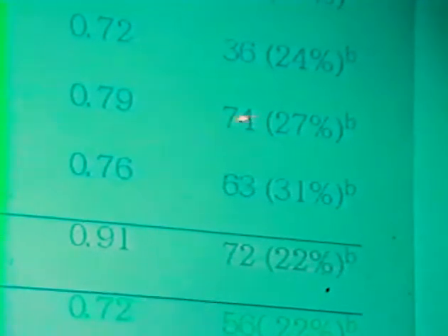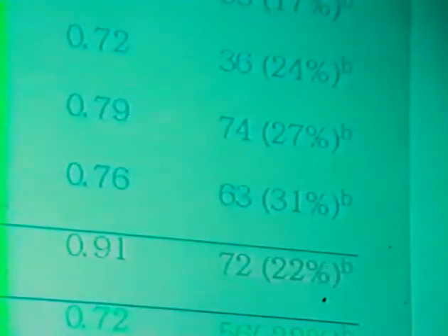And in fact, we get about the same selectivity. But if we look at the relative conversion at 15 minutes and 50 minutes, which is some measure of the self-poisoning by coke, the smaller particles appear to be more stable. They retain about 90% of their activity over this period of time, while this retains only about 80%.